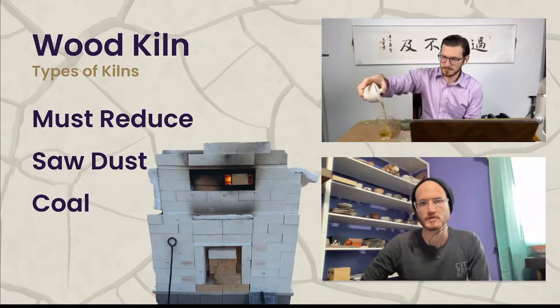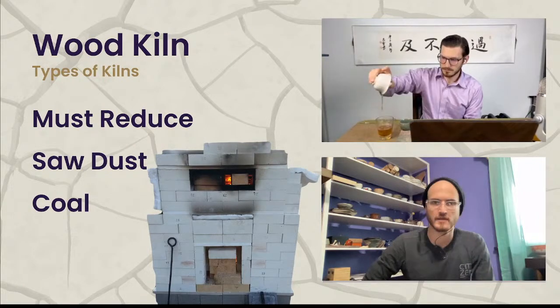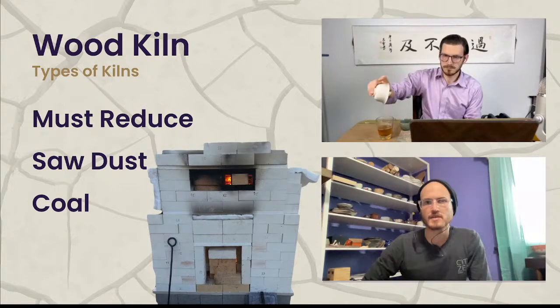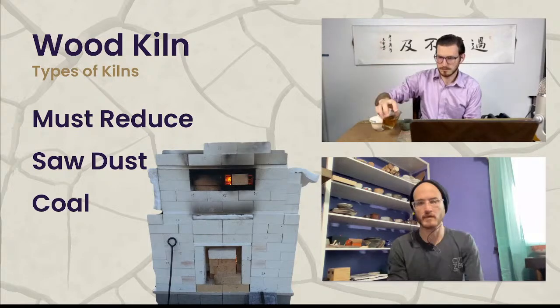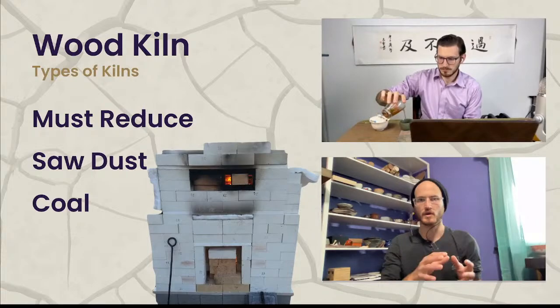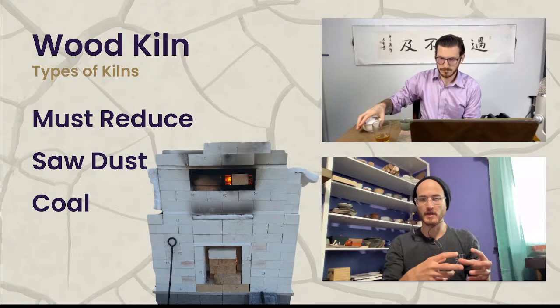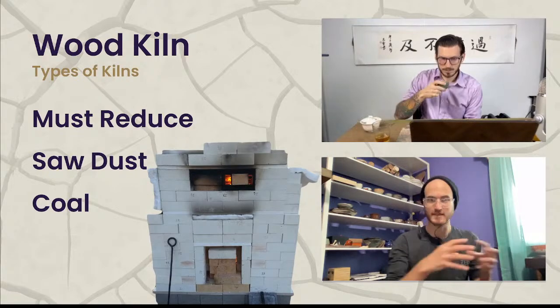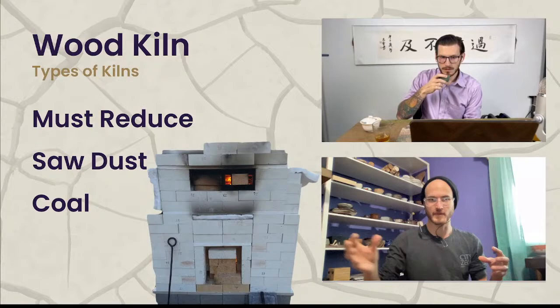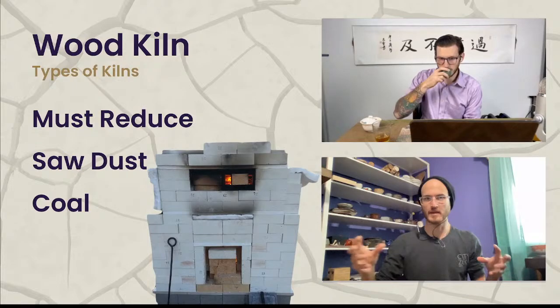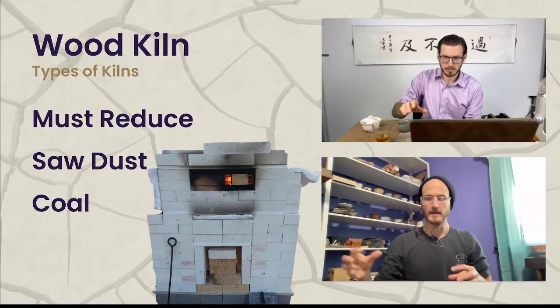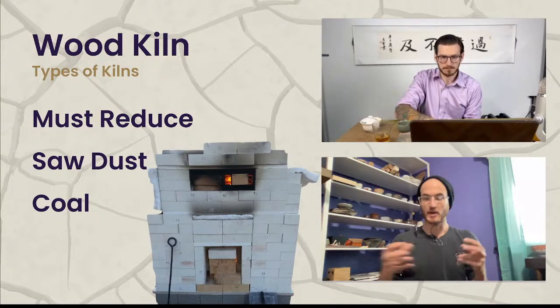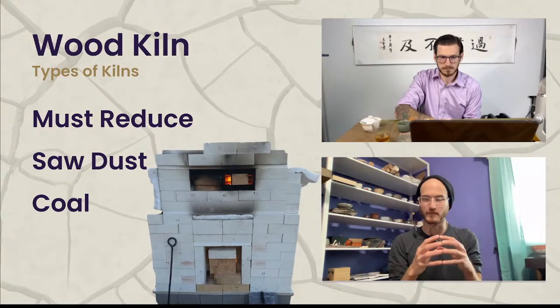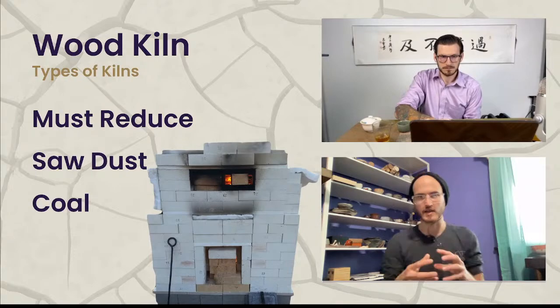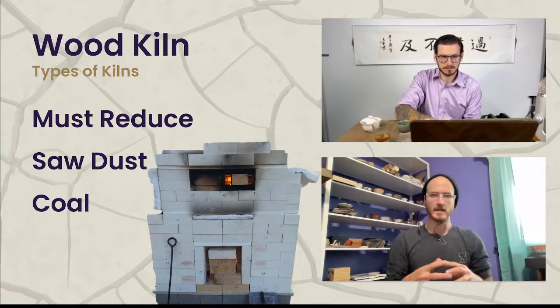So yeah, wood kilns are kind of a special case, and it's more or less the reason why potters want to reduce inside of a kiln environment, and it's because when you introduce wood, as the wood is burning, the first thing you get is all of the liquids inside of the wood that are burning off, and that causes a very turbulent and smoky kiln atmosphere. And when you have all of those different chemicals that are going through the kiln and not just the heat of flame, you get a lot of reduction. So it's a lot of ionic interaction and oxide interaction between the clay and the glaze and the atmosphere of the kiln.